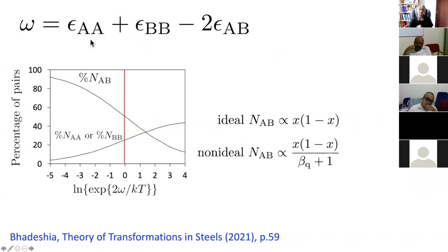omega here is a reflection of the change in bond energy when we break an AA bond and a BB bond and create two AB bonds. In other words, this determines your enthalpy of mixing. And this is a parameter which is a function of enthalpy of mixing. When enthalpy of mixing is zero here, the number of AA bonds and number of AB bonds is simply given by probabilities. So the number of AB bonds will be proportional to the chance of finding an A atom multiplied by the chance of finding a B atom, and multiplied by 2 because we can have AB and BA bonds. And the number of AA bonds would simply be x squared, number of BB bonds would be (1 minus x) squared. So that corresponds to these two points on this diagram.